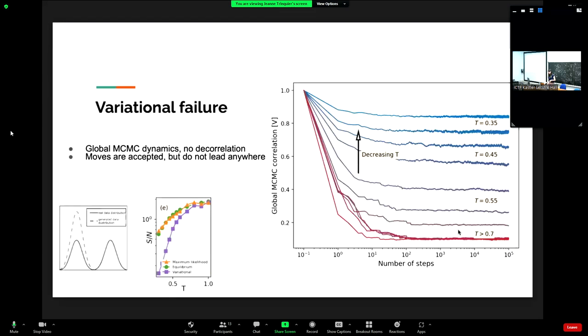And the variational approach also failed, but for different reasons. In this case, you are able to get a good acceptance rate doing this global MCMC dynamics, but actually you don't decorrelate. You can see it in this plot. The red line is a high temperature, where you are able to decorrelate. This is the number of steps in your global MCMC, but you see that for lower temperatures, you basically stay at one, so you don't decorrelate at all. That's because you are just learning a very small portion of the landscape, and so you are just staying in this very small region.